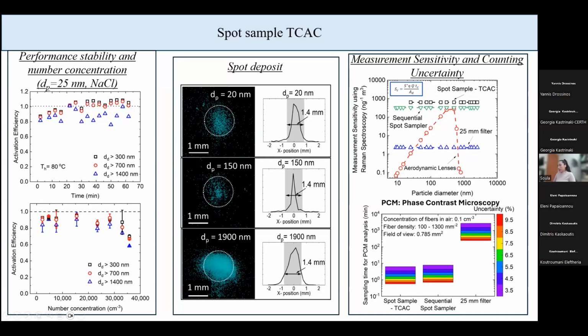And finally, I did some calculations. There is a NIOSH method specifically for fiber counting when we use phase contrast microscopy. Specifically, how do we do that? We first collect the sample on a 25 mm diameter filter. Then we put the sample under the microscope. We zoom in on an area of 0.785 square millimeters, and we count manually the fibers that we see on it. So the method proposes an optimum fiber density of 100 to 1300 fibers per square millimeter to achieve a counting uncertainty between 3 and 10%.